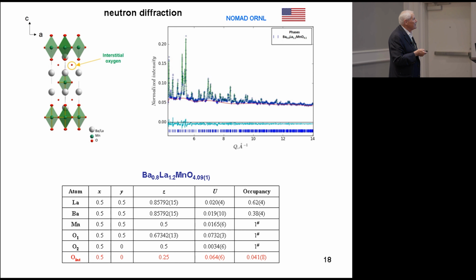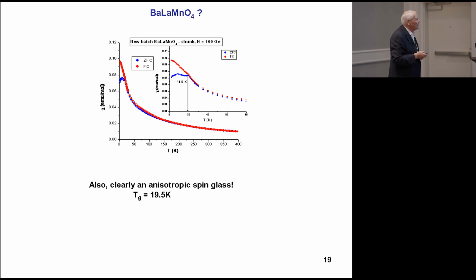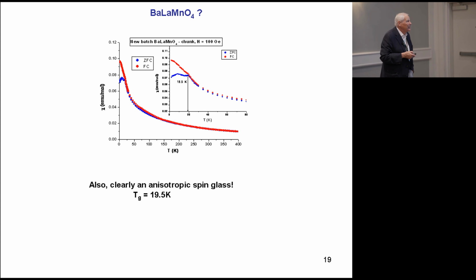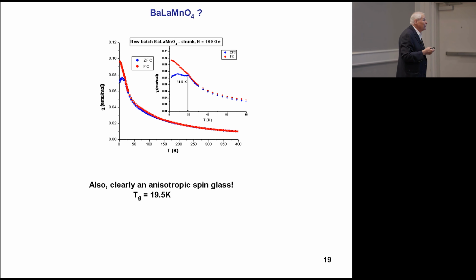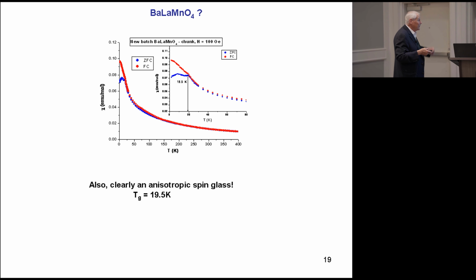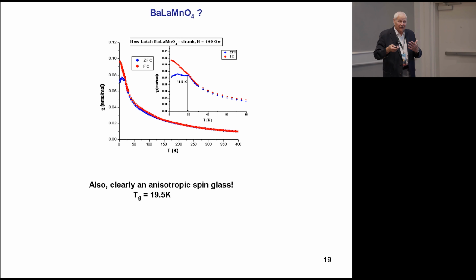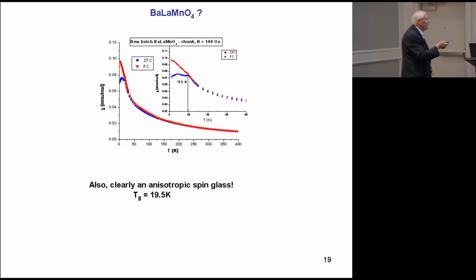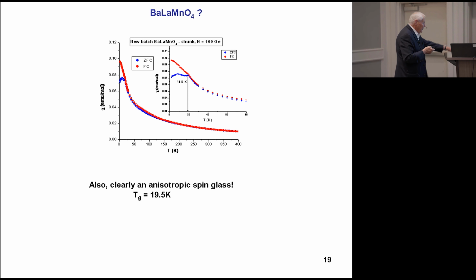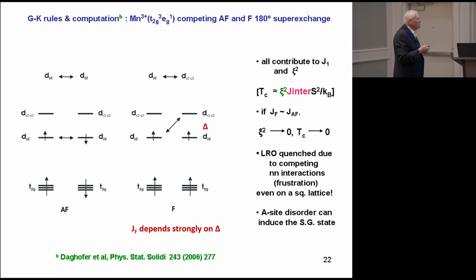Ruddlesden-Popper manganese phase. Okay, so what is the story with barium, lanthanum, and manganese oxide? We couldn't get a single crystal, but of course we could get powders. And when we obtained the powder data, it looks exactly like we expect for a powder sample of the anisotropic system. So finally we understand that the all barium phase is an anisotropic system. And how can we justify this? Here's an attempt.